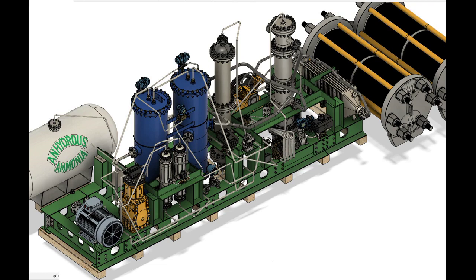For small-scale plants, it may seem at first glance that a more moderate pressure is desirable from the perspective of component sourcing, since the cost of high-pressure rated components is proportional to their mass, which is then directly linearly proportional to the pressure they must withstand. On the other hand, these higher pressures permit a considerable reduction in the scale of the components, since less catalyst is needed, reducing the material required even though thicker walls are needed. A fine balance between these two variables must be struck. The principal advantage of lowering the pressure is minimizing nitriding as well as maximizing the catalyst longevity.